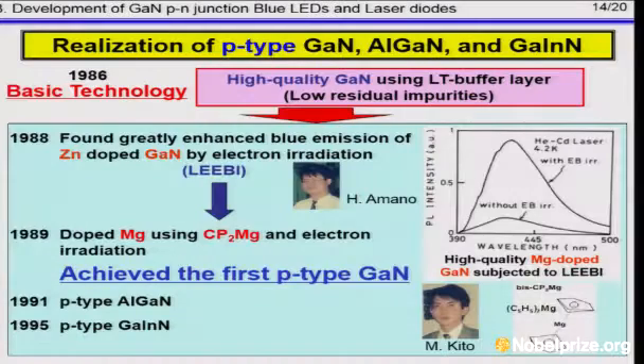Let's turn now to the realization of P-type conduction in gallium nitride. To realize P-type conduction, we repeated zinc doping of high-quality gallium nitride, but no P-type gallium nitride was produced, although the crystal became highly resistive.